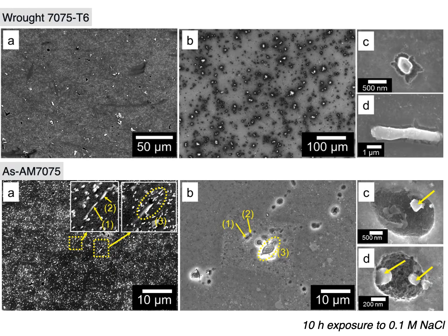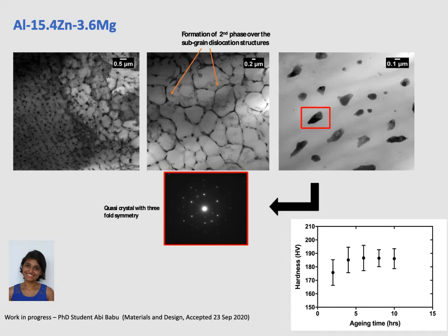All right, so corrosion-wise, we see very low rates of corrosion relative to wrought 7075 when we look at the 3D printed 7075. And here I show the analysis using post-immersion scanning electron microscopy, where the remarkable thing is that the size of the pits in the 3D printed 7075 are essentially, and in fact always, submicron and superficial in nature, which is quite remarkable.